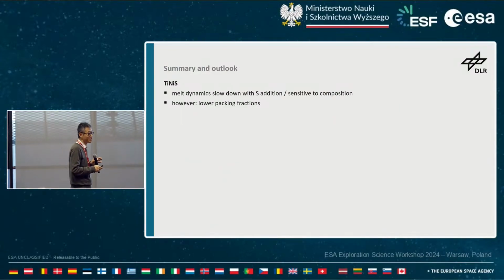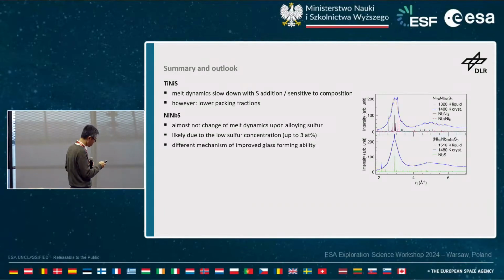So this will be my summary of the first part, just to show you a contrast of these two samples. For the titanium base, where the sulfur content is higher, we do see a change of the liquid dynamics. For nickel-niobium sulfur alloys, we do not see much change in the melt dynamics with sulfur alloying, but it's likely due to the low sulfur concentration. This means we are expecting a different mechanism for why the glass forming ability is changed compared to titanium nickel sulfur alloys.